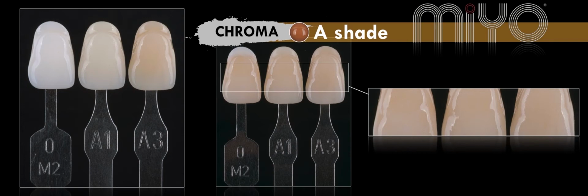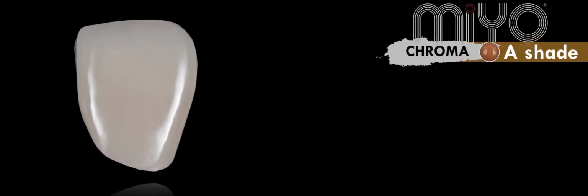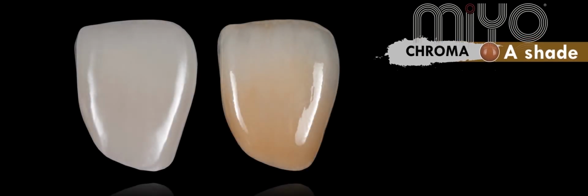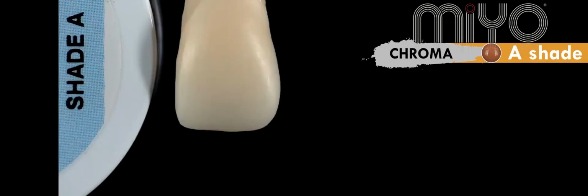And that's important because people obviously will say, well, how many coats did you put on? How much color did you have to apply to build that up? And like James said, these are plastic tabs, so clearly not fired. And this is a very simple, thin application of 1 coat. And even the OM2, pretty good match for an A3. So you can see here, we started with the A1, a multi-layer A1, and reached somewhere between A3 and A3.5 with 1 firing.